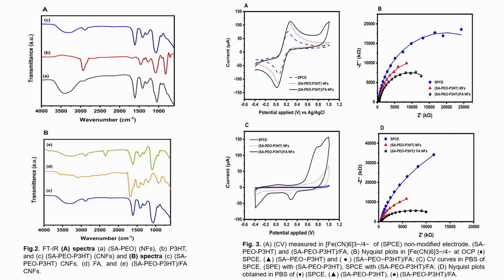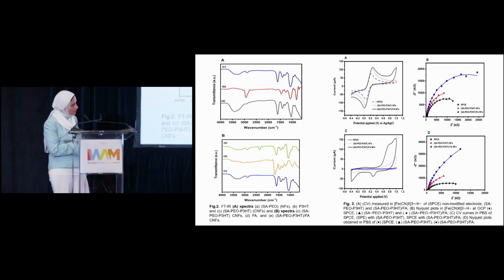Here I want to point to this electrochemical characterization in a solution containing a redox marker, ferro-ferricyanide, and in another one without any redox marker, depending only on our conjugated polymer. As we see the same behavior, there is an increase in all the signals of cyclic voltammetry, which confirmed that we can depend on the redox activity alone, without any redox marker, to follow the interfacial change on our electrode. The same behavior appears in the impedance: as we know, if the current increases, the resistance to charge transfer decreases. So the impedance decreased gradually from the screen-printed electrode and after modification with conducting nanofibers, and decreased more and more after conjugation with folic acid in both solutions.